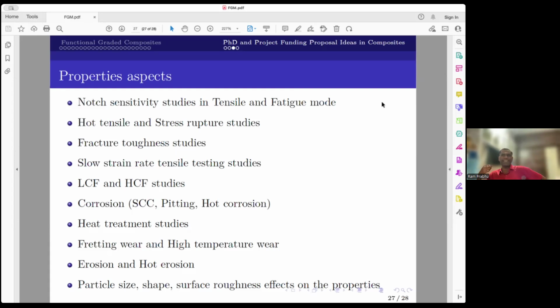Then studying the property at higher temperature, like a hot tensile or the stress rupture test, and understanding the fracture toughness, like what I showed you in my SEM graph. When you do the 3-point bend test, when the crack touches a soft region like a copper region, the crack branching happens, improves the toughness. So those kind of studies.